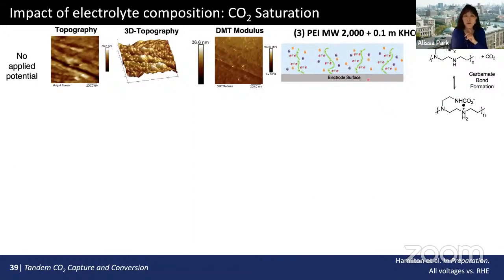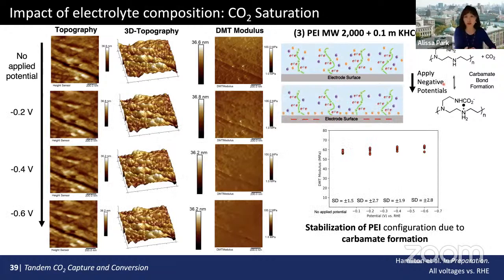But an interesting thing happened when we had the same system, and now we saturated this entire system with carbon dioxide. With all this carbon dioxide surrounding this polymer, PEI, as we applied the potential, it was very different. Its deformation did not change, meaning the conformation of these polymers on the electrode surface wasn't changing much. So when you try to really understand what's happening at electrode interfaces, having the system with the electrochemical potential in AFM or any other measurement in situ is very important. This information will tell us how CO2 gets delivered to the surface of the catalyst and converted to products.